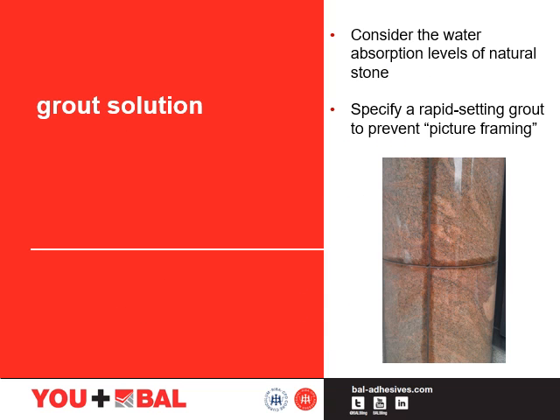When grouting natural stone, it's important to consider the water absorption levels of the stone. In order to minimize any risk of possible picture framing — where the edges of the tiles are stained by water from the grout penetrating the surface — we must specify a rapid setting grout. Depending on the substrate and surface condition, a flexible grout might be required. We can either use the built-in admix version or a two-part powder and admix version. As a general guide, the colour of the grout should complement the colour of the stone tiles and not significantly contrast, to avoid the risk of staining.